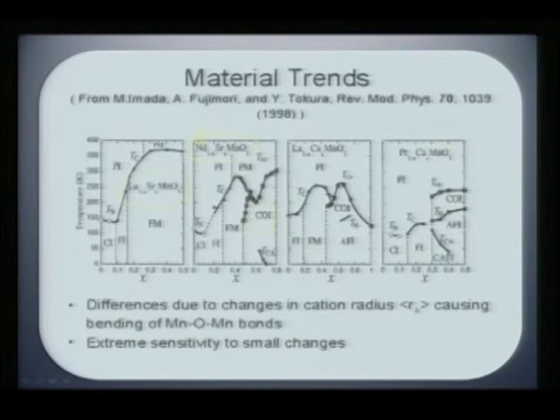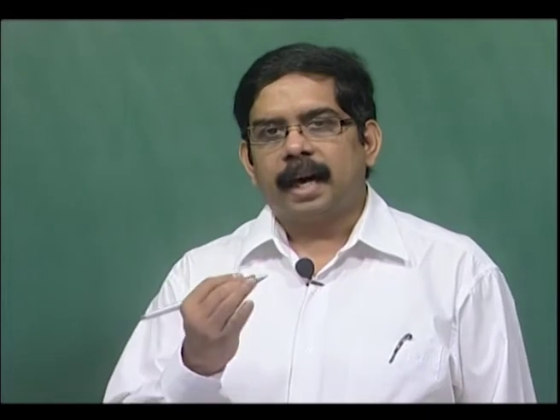Similarly the case for praseodymium, it is more complex than other series because praseodymium itself has a variable valency. As a result, the MIT and ferromagnetic transition gets distorted. So, differences due to changes in cationic radii Ra bring about a charge ordering because there is bending of Mn-O-Mn bonds. So, when Mn-O-Mn bonds are distorted or deviate from 174 degrees as I told you earlier, then you would actually go into a charge ordered state, okay, which means there is a competing interaction between the itinerant electrons